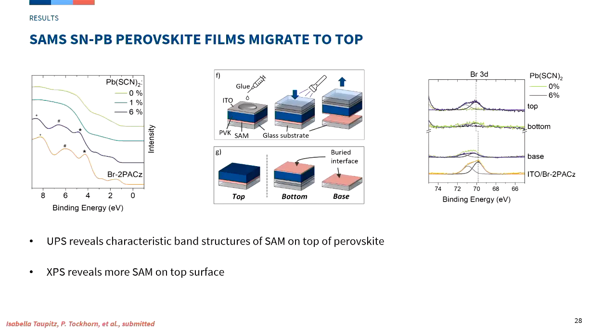Basically what we find as a summary is if you use the additive, you peel off, or resorb the self-assembled monolayer and the molecule at the bottom, and bring it to the top. If you do so, then you have a well passivated perovskite that has the hole selective contact on both sides. So this is not a very good solar cell anymore. It's not a diode anymore.